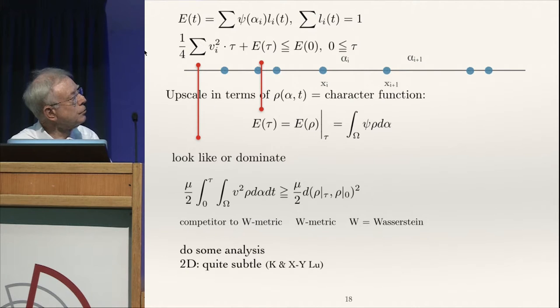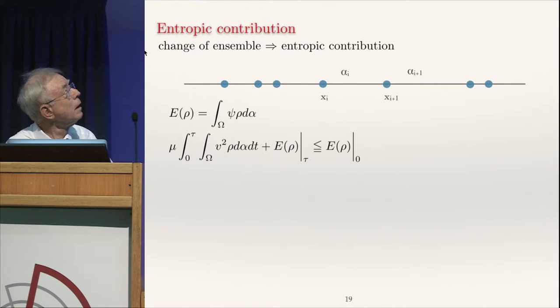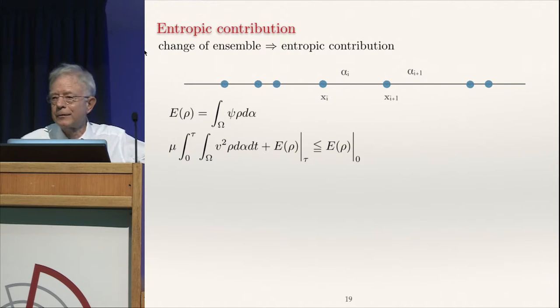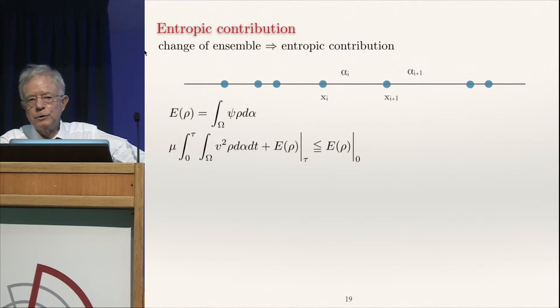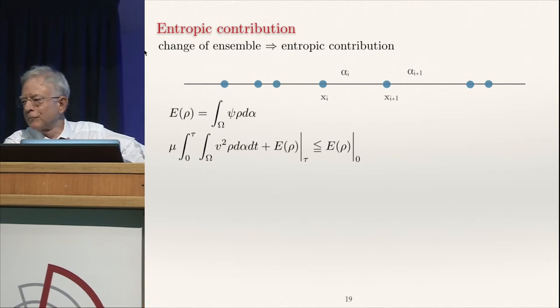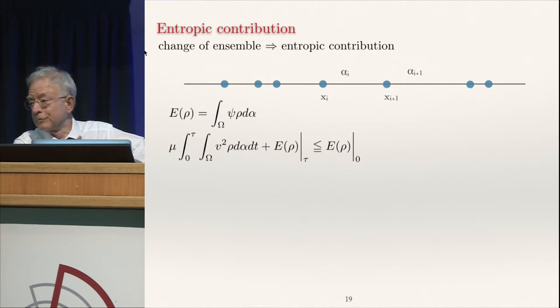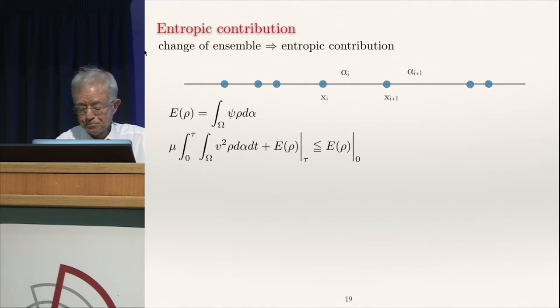So we do some analysis here, and in 2D, this is quite subtle, but this was done by Xinyang Lu. We must add an entropic contribution. So the entropic contribution is due to the fact that the ensemble has changed. We change the ensemble, you have to account for that. That's the origin of entropy, right?